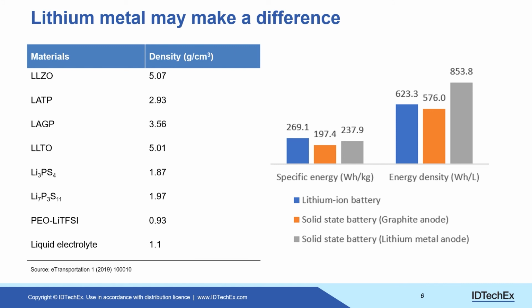If we just use the graphite anode with the solid-state electrolyte, then both the volumetric and the specific energy density actually have a drop compared with the lithium-ion batteries. Even when you replace the graphite anode with lithium metal, you can still see a slight drop for the specific energy. That is for the case of the LLZO. And because the density is really high, the target thickness should still be smaller than 40 micrometers in order to really get a benefit in terms of energy density. So in the future, lithium metal will make a difference for the cell. That is a really important trend.